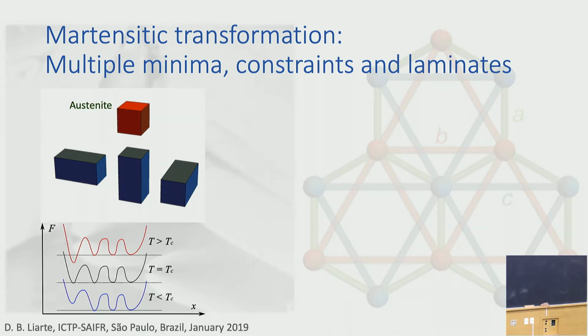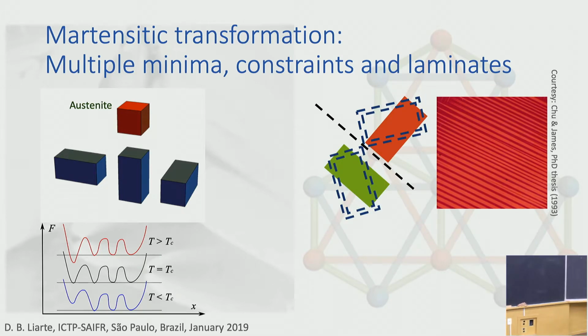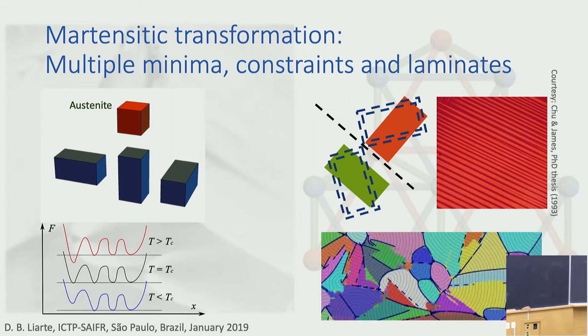Now imagine that you do this experiment with your crystal while constraining the boundary conditions so that the net strain doesn't change. So you do not allow the whole material to elongate some distance. It's fixed. What will happen is that these variants, these 3 different variants, some regions will like to deform along one direction, some regions will deform along another direction. And these variants will rotate, forming these string boundaries, forming these fine laminates that are shown here. So what I'm going to show you in the next slides of this part is that you can see the laminate microstructure as a kind of Martensite, and how you can interpret them as a Martensite.